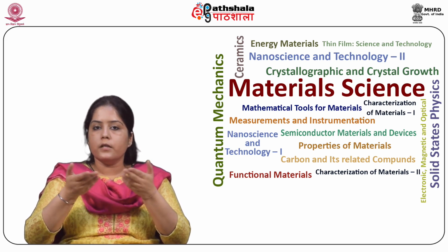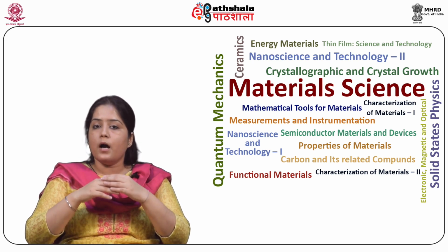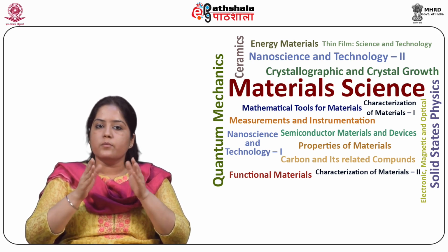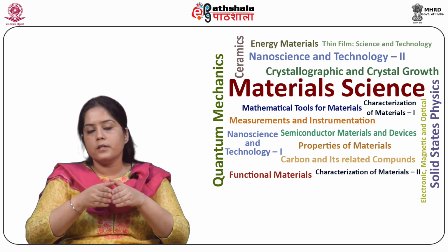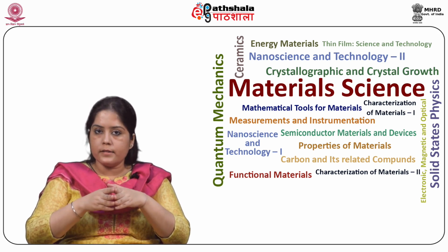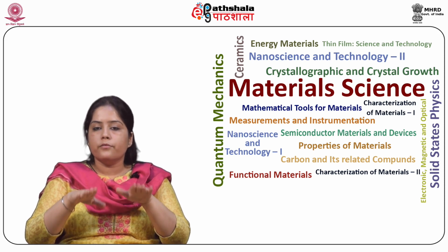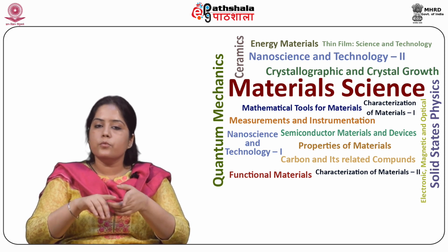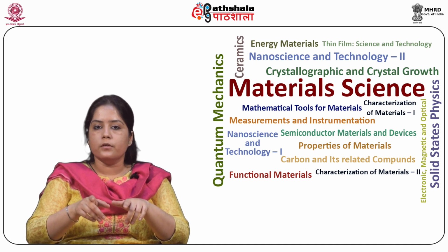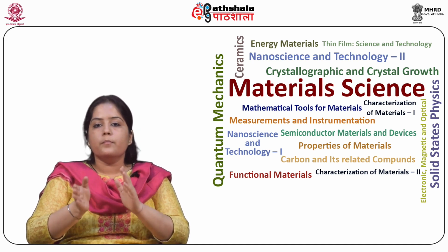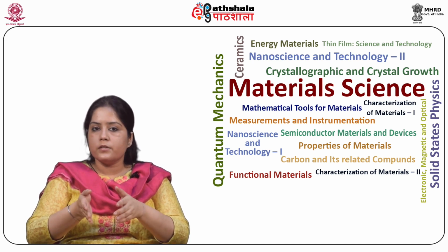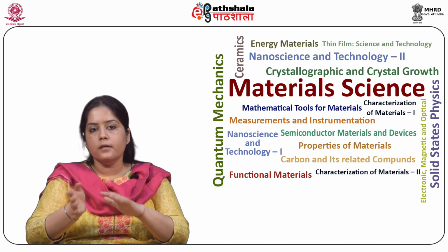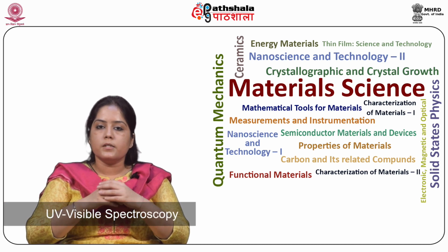For example, in VRFB, the vanadium ion permeability measurement typically involves measuring the diffusion rate of vanadium 4 ions across the membrane from a 1 molar VOSO4 and 2 molar H2SO4 solution on one side to a blank 1 molar MgSO4 and 2 molar H2SO4 on the opposite side, using UV-visible spectroscopy.